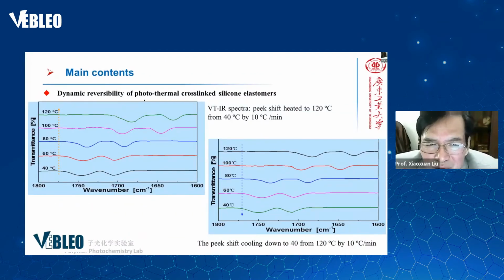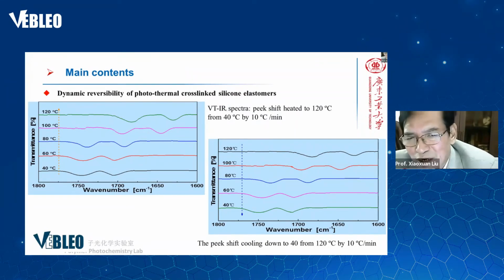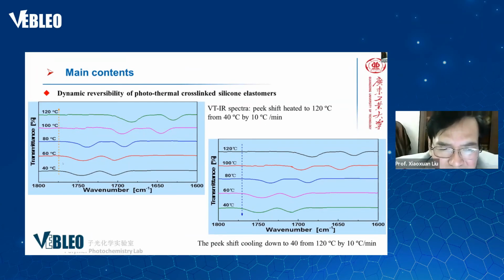So, the dynamic reversibility of the photo cross-linked silicone elastomer. We use variable-temperature infrared spectra. The peak shifts as heated from 40 degrees centigrade to 120 degrees centigrade, with a heating rate of 10 degrees centigrade per minute. The carbonyl absorption band changes and shifts.